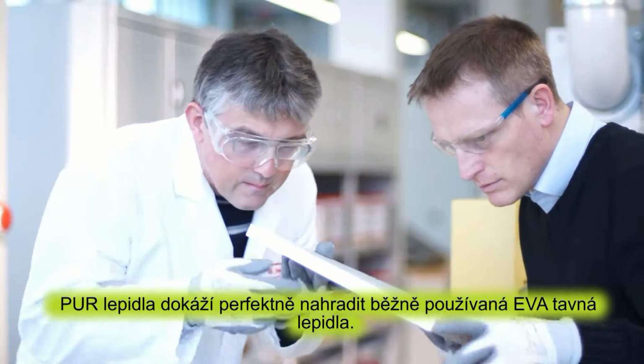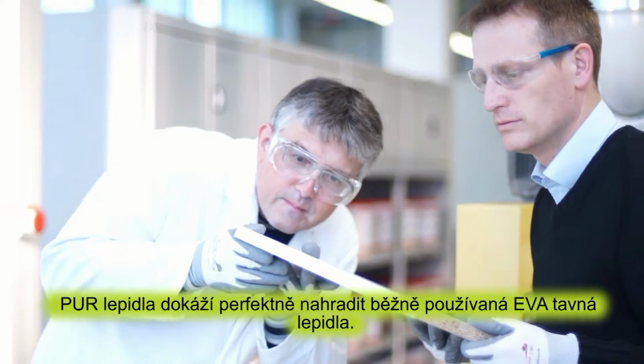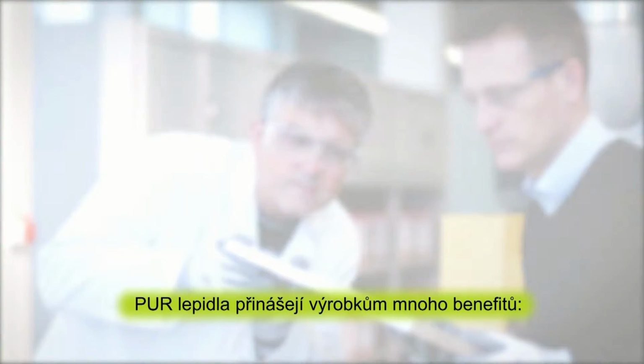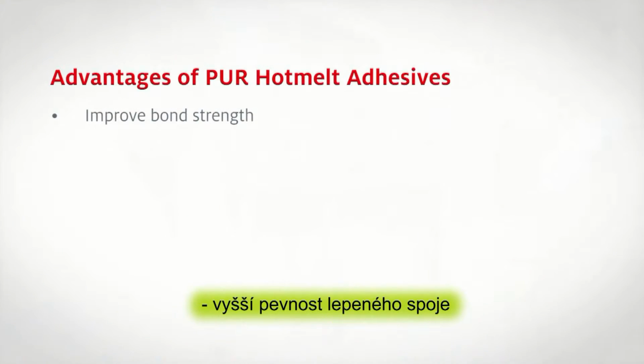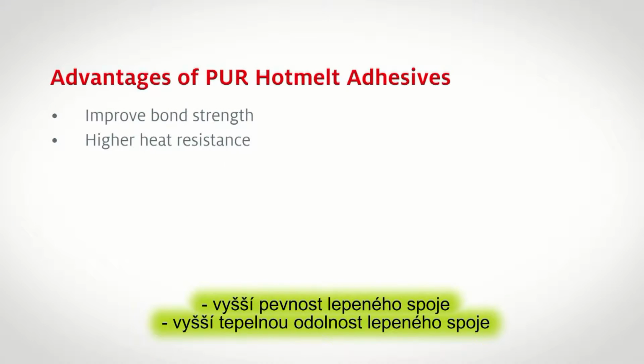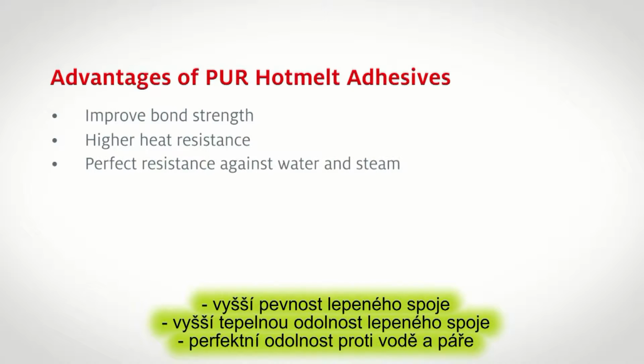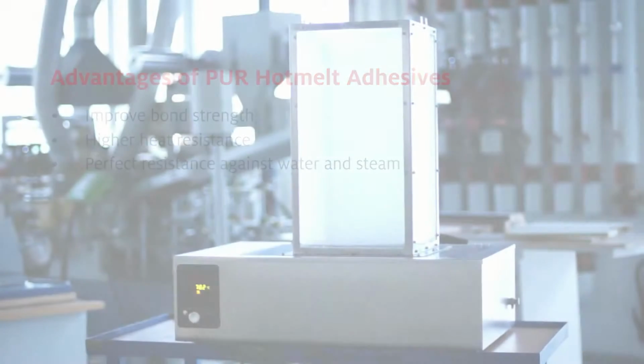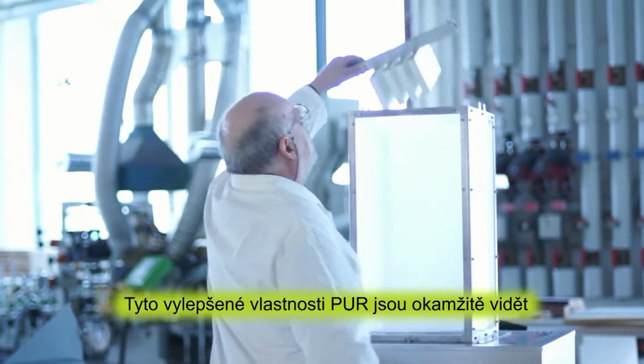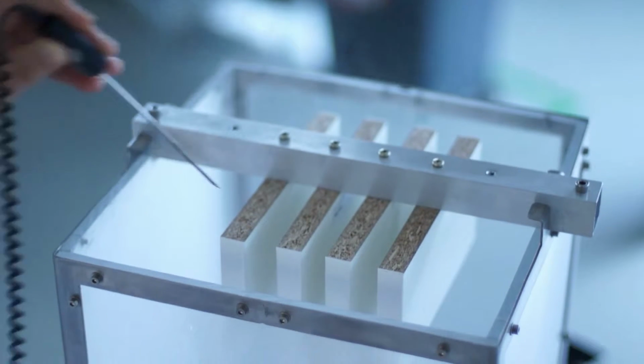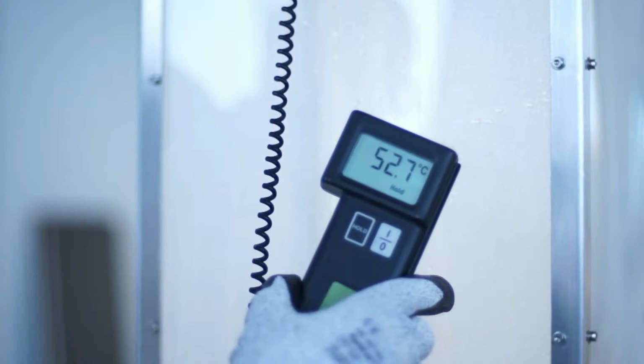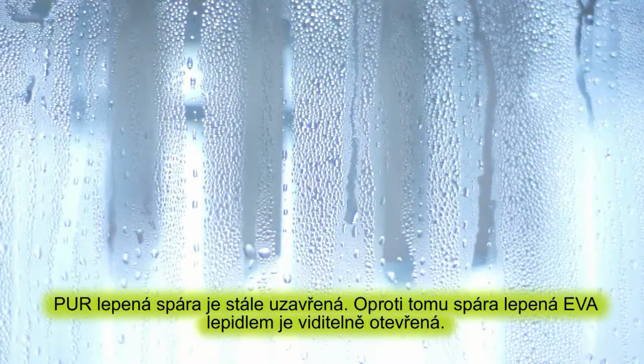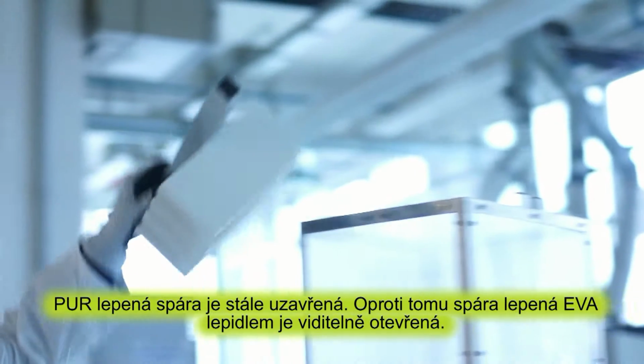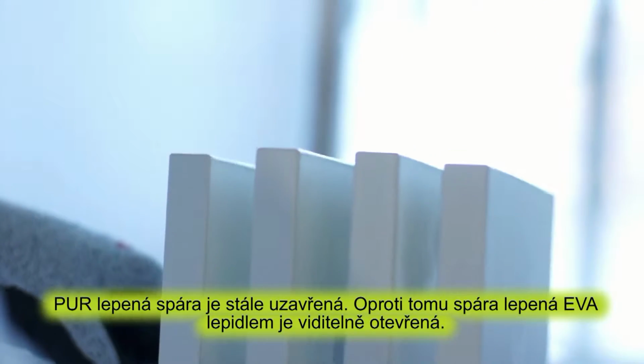PUR perfectly replaces conventional EVA adhesives. What's more, PUR excels in many regards, with an improved bond strength, higher heat resistance, and perfect resistance against water and steam. The advantage of PUR is immediately visible after having passed the water and steam test. The glue line is still closed with PUR, whilst open glue joints are visible when having used EVA.